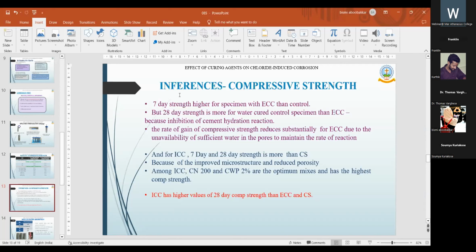And for integral curing compound, the 7-day and 28-day strength is more than the control specimen, and this is because of the improved microstructure and reduced porosity.